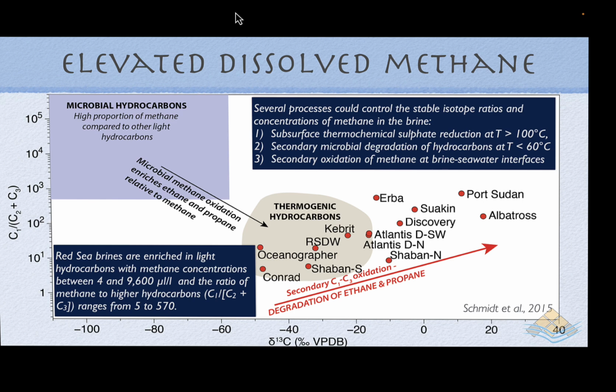Several processes could be controlling the stable isotope ratios and the concentration of methane in those brines. It could be the result of thermochemical sulfate reduction, which requires temperatures in excess of 100 degrees centigrade. It could also be related to the secondary microbial degradation of hydrocarbons at temperatures of less than 60 degrees, or the secondary oxidation of methane at brine-seawater interfaces. These are all possibilities. But what's interesting here is that we very likely have a thermochemical input into these brines, not the standard microbial origin of methane.